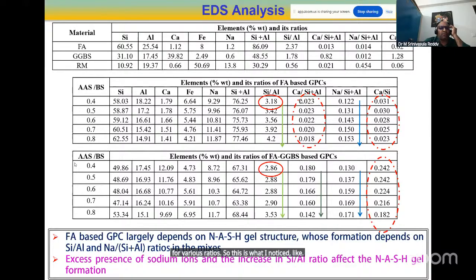As this is increasing, the calcium to Si plus Al ratio is decreasing. So with the decrease in this ratio, I notice a decrease in the strength. When the Na by Si plus Al, the sodium content, is increasing, that is also affecting the geopolymerization. That's why there is a decrease in the strength. So initially I told that further increase in the molarity, or further addition of more sodium silicate and sodium hydroxide, is inhibiting the geopolymerization process. You can notice this here from the EDS analysis. With the presence of more amount of AAS, the Na to Si plus Al ratio is increasing. That is hindering the process. That's why we are getting less strength.